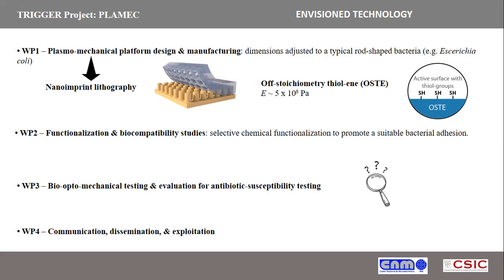On the one hand, it has a low Young's modulus, close to PDMS, a bit higher. And also, very interestingly, it has complex surface chemistry that presents thiol groups on the surface, which may facilitate the interaction of the polymer with the gold that has been deposited on the silicon master. In addition, it can be processed by photolithography, allowing a scalable fabrication of the devices.